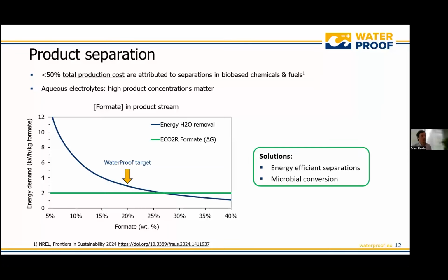What you can see in this graph below is that I graphed, the blue line is showing the amount of energy it takes to remove water from a formic acid stream. And then on the x-axis is its respective concentration. So you can see that as you go to more and more concentrated electrolytes, your energy demand gets lower and lower. And in the WaterProof project, we're aiming for approximately 20 weight percent formate, as we think that this is a realistic process target for this concentration.